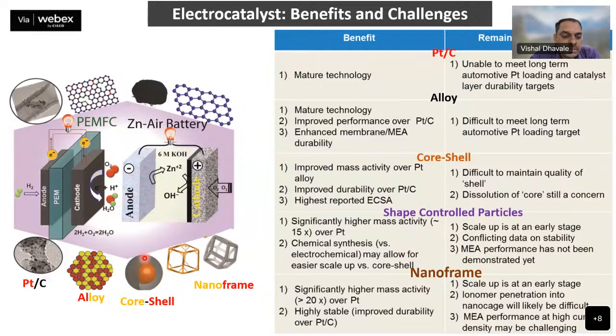Next, in the next generation of electrocatalysts, core-shell catalysts have been reported by researchers, where the inner core of the particle is replaced with a very cheap transition metal, covered by a thin layer of platinum shell, which tunes the electrocatalytic activity of the shell and significantly enhances the activity and stability that researchers expected. But there are some challenges with core-shell electrocatalysts, like the difficulty in maintaining the shell thickness, and continuous shell formation on the cheap transition metal is a tedious task. Furthermore, scalability is another issue.